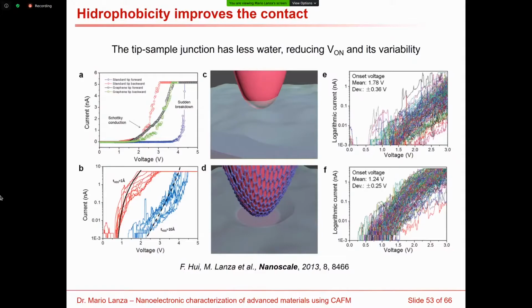We also found, unexpectedly, another very interesting property. When we perform statistical analysis of the many IV curves with both types of tips, with and without graphene, we observe here in panels E and F that the onset voltage of the graphene-coated tips is always a little bit lower, and that the deviation is also lower. And the reason, as we found later, thanks to some friends who helped us to do some simulation, is that we conclude the graphene helps to avoid the formation of a water meniscus, or at least reduce it at the tip-sample junction, because graphene is a hydrophobic material.